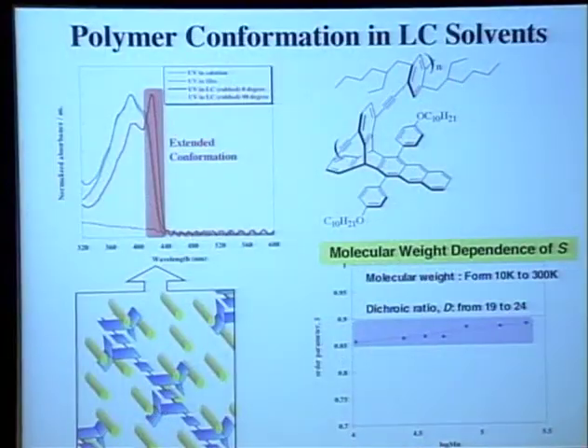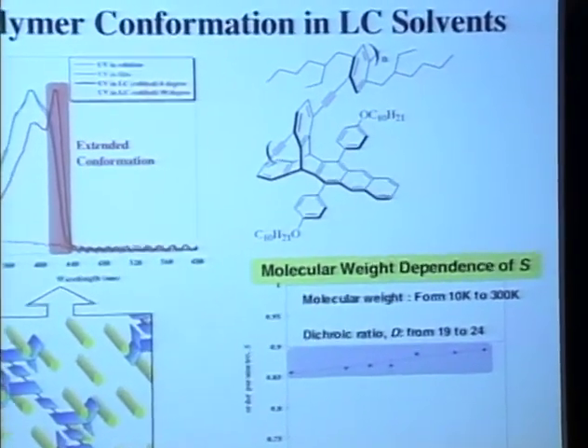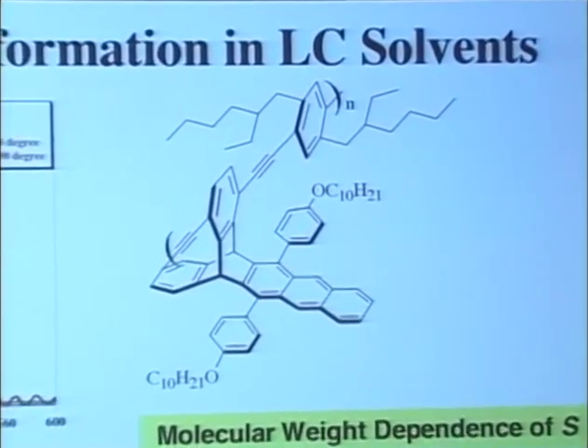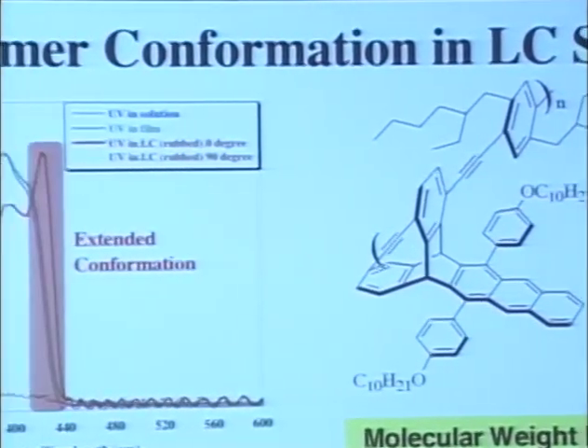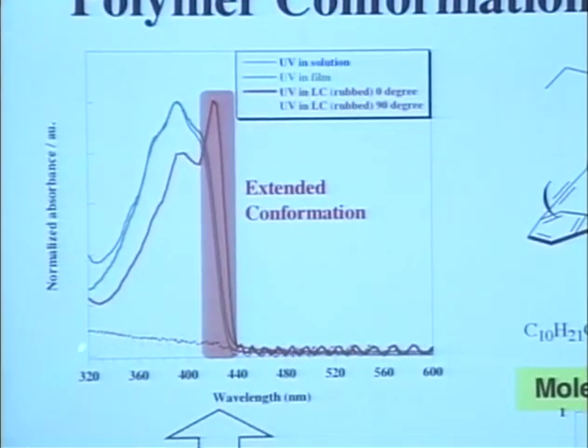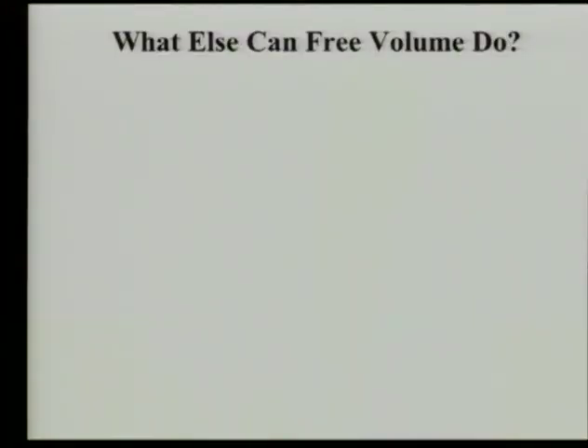Now, one of the other things I like about this in terms of my electronic life is that when we put these molecules in liquid crystal, you can see that there's a spectroscopic change. The red and the blue, the green and the blue trace here are in solution and in thin films. But when we dissolve the polymer into a liquid crystal, we get a different spectrum. And that spectrum is because the molecule has a very long planarity to it, and that gives a greater electronic coherence along the molecule length, and that is good for doing molecular electronics. That is what you would like. You would like your electrons to be able to just whiz through it. There's essentially one coherent state across your device, and this is what you would like for devices. And again, we can make devices that have very long molecules and sometimes very short molecules.